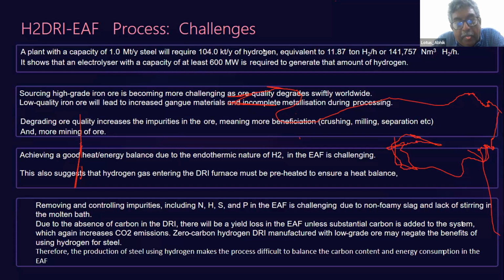So due to the absence of carbon, and carbon actually does a lot of things. Carbon is a reducing agent. Carbon, it is an exothermic reaction. It gives heat to the furnace. It reduces that extracted iron from the oxide. And also carbon stirs the molten metal, like if you stir the milk, that uniformity will be there. So carbon stirs it, but hydrogen doesn't do it. So as it says, due to the absence of carbon, there will be yield loss, unless substantial carbon is added to the system. So you have to add some carbon to start it, which again increases carbon dioxide emission.